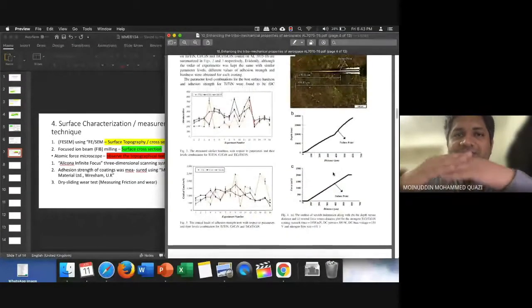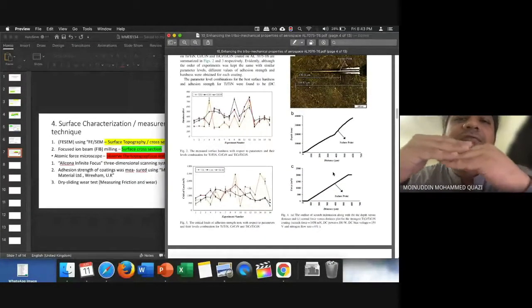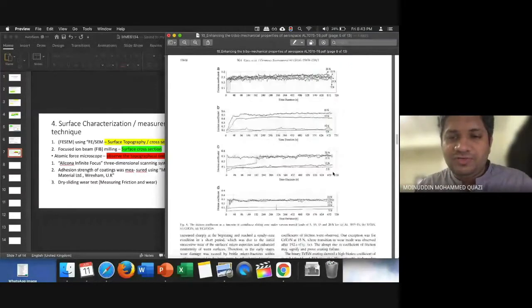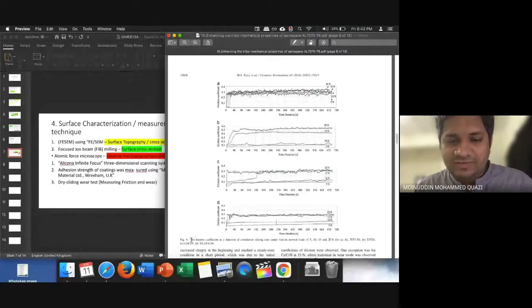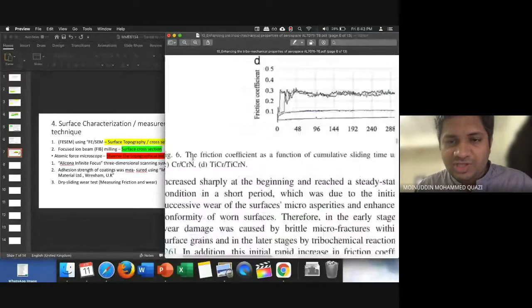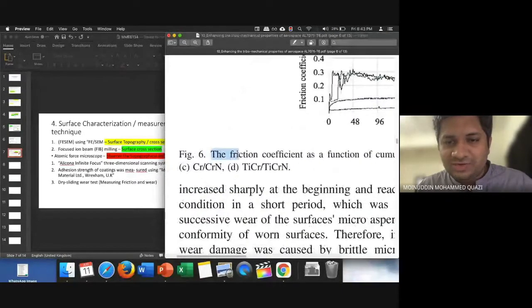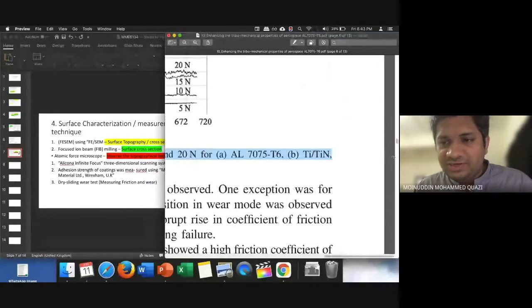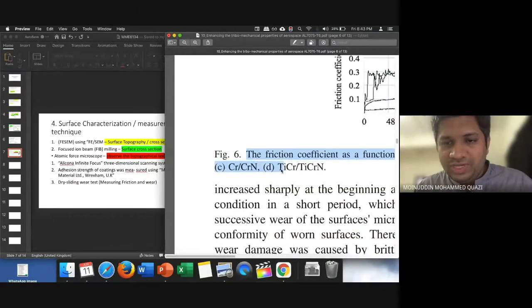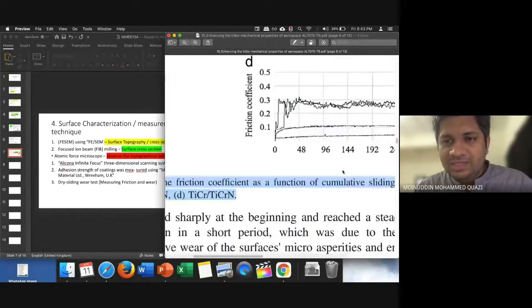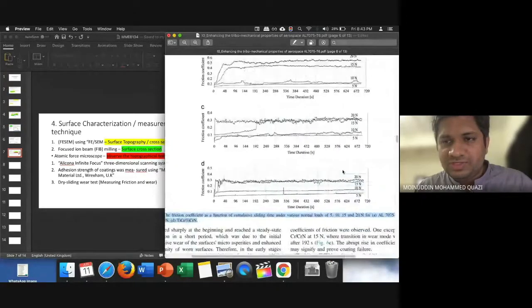In wear testing, you get the value of friction coefficient and amount of wear. So the friction coefficient is here. The friction coefficient as a function of cumulative sliding distance. Friction coefficient as a function of sliding distance for substrate, coating number 1, coating number 2, and coating number 3. So friction coefficient.